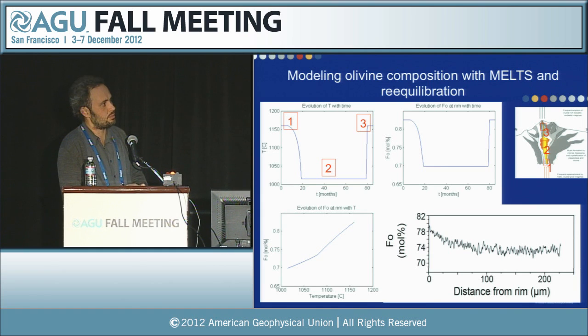I see now there's a little bit of a misfit between this plateau and this one, but it doesn't matter. We just have to stop at higher temperatures, because what we want is a plateau here at 74, which is this plateau here, and then this 79, which is a little bit higher, so it should be about here. That's what we're trying to fit: that this plateau here should have grown at this temperature. This is what MELTS says. It doesn't say when, it just says that it should have grown at this temperature here. And then this part would be growing here.